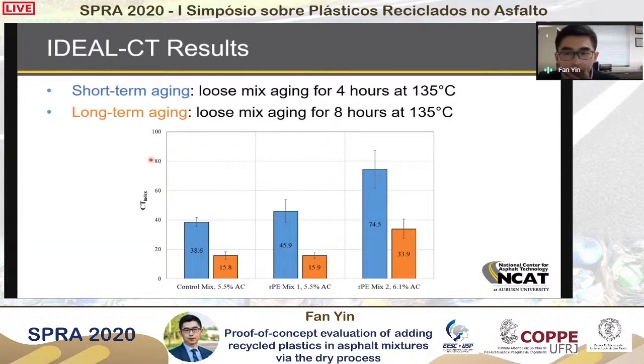Now, if we look at the results for the IDEAL-CT, we look at two aging conditions. We definitely recognize the importance of asphalt aging on the cracking evaluation, so we look at the short-term aging and long-term aging conditions in the same test. Once again, there are three mixes, the same mixes we have been using in this example. For each mix, the blue bar is the short-term aging and the orange bar is the long-term aging. So this one is the control.